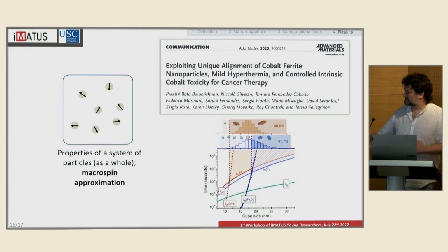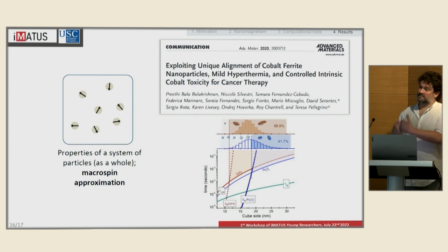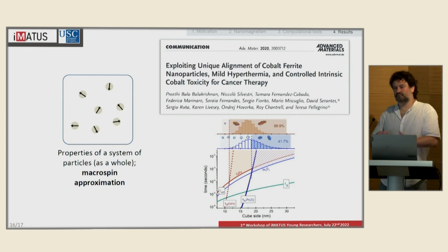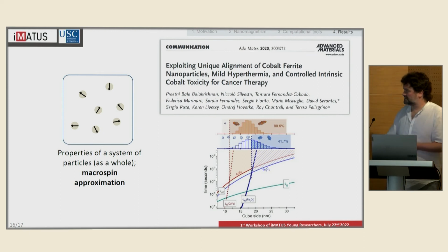This collaboration was motivated because, when delivering magnetic nanoparticles of cobalt ferrite or iron oxide within cells, with a slightly bigger particle size for the iron oxides, the spontaneous formation of chains was observed for the cobalt ferrites, but not for the iron oxides. So we developed a model to explain this based on the likelihood of agglomeration depending on the stability of the magnetization, but the details are there.